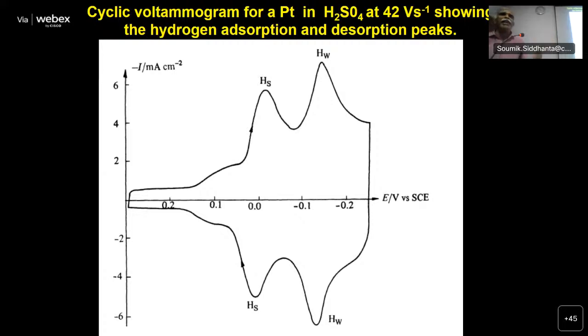Because I can understand what type of hydrogen adsorption happens on polycrystalline platinum. I have HS, HW. Hydrogen is giving me a voltammogram where the oxidation peak and the reduction peak happen at the same potential. When the peaks happen at the same potential, this is a typical signature of surface confinement, something attached on the surface, nothing diffusing at all. These symmetric voltammograms where the oxidation and reduction happen at the same potential, this is a telltale feature of adsorption. So here we have HS and HW, two forms of adsorbed hydrogen, both happening on polycrystalline platinum.